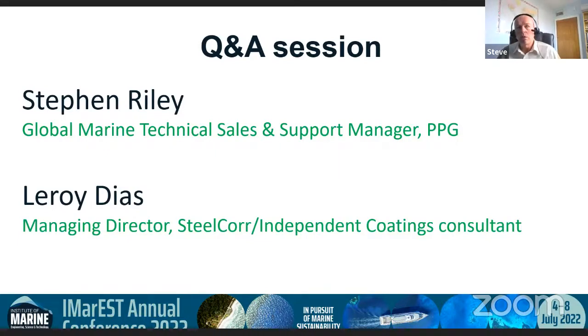Because some rely on a biocide to provide performance. If you think about a silicone matrix, I've shown you the way the water resists interaction with silicone. But then you've got a water-soluble biocide in the coating. You have to do some chemical trickery to get water into the coating to get the biocide out. So you get a difference in performance between the two systems, even though they're loosely defined as silicone coatings. Correct. Yeah. All right.